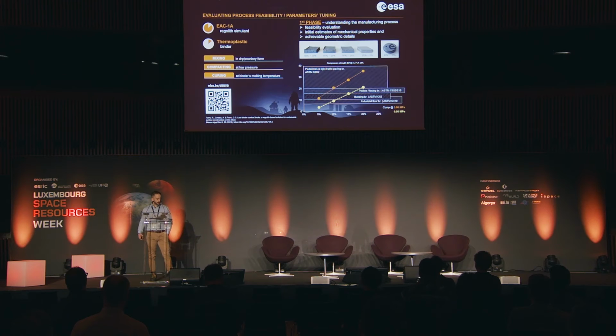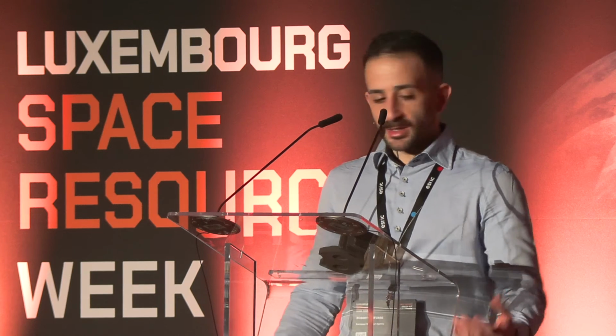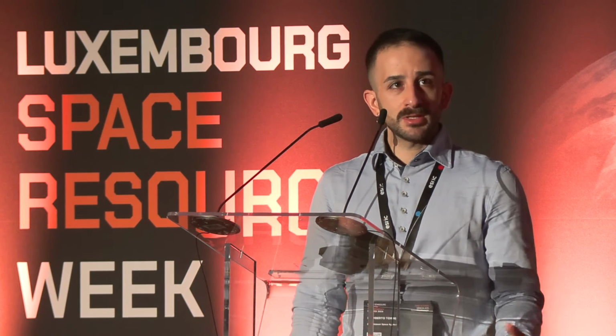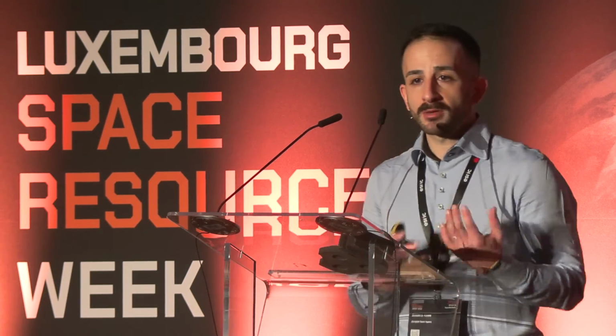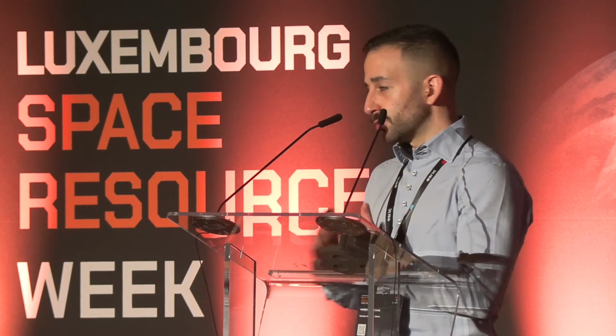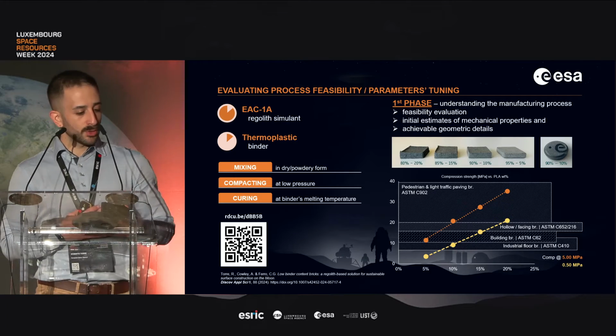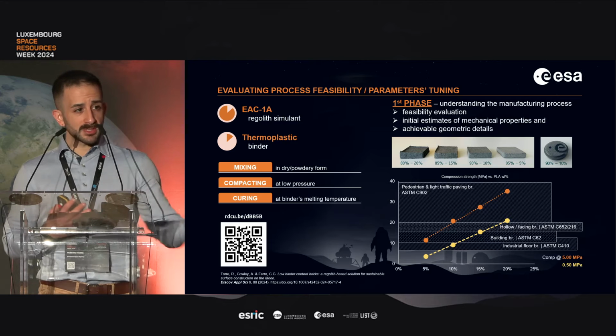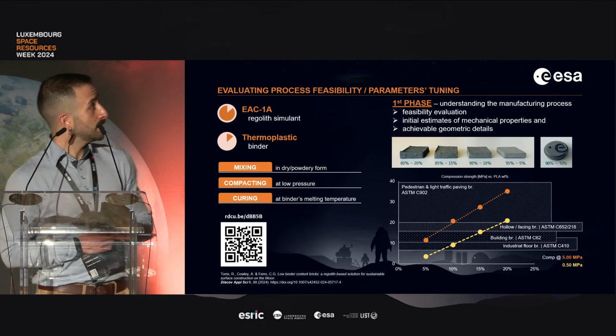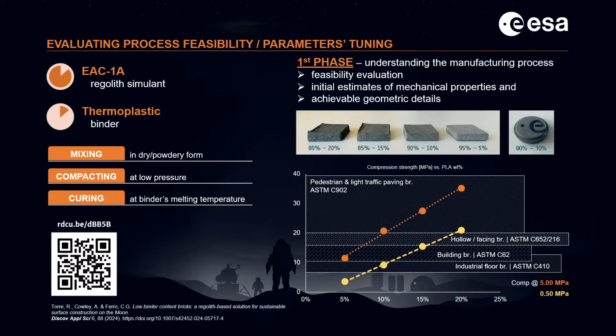As a first step of the process, we wanted to understand its feasibility. We wanted to understand which mechanical properties we could achieve, and also which kind of geometrical details we could have. You see from the picture that we managed to go as low as 5% in binder content, which means 95% regolith. And from the ESA logo you can see on the right, imagine that it's 6 centimeters in diameter. So you can realize that we can really have fine details, sharp angles, and thin surfaces.